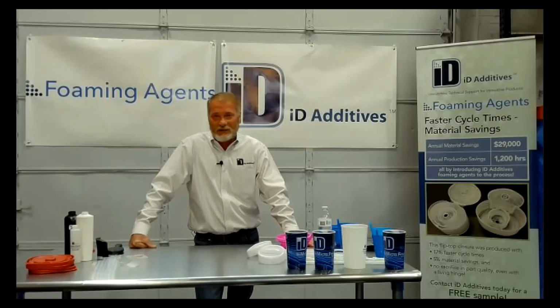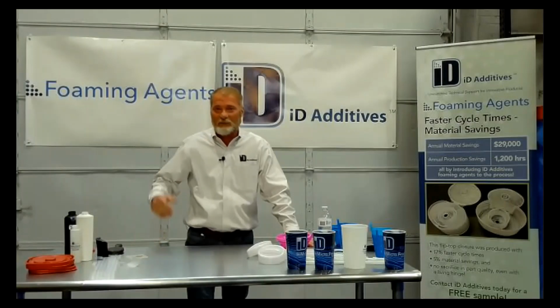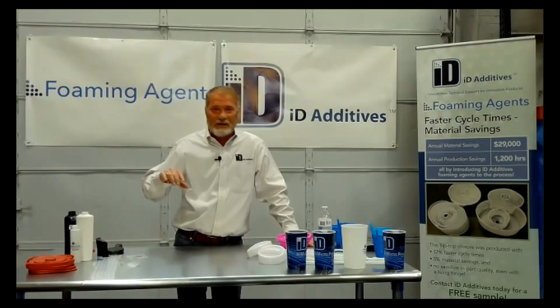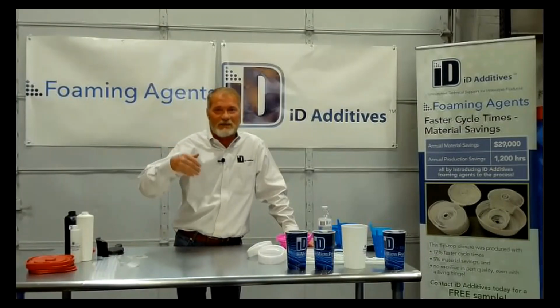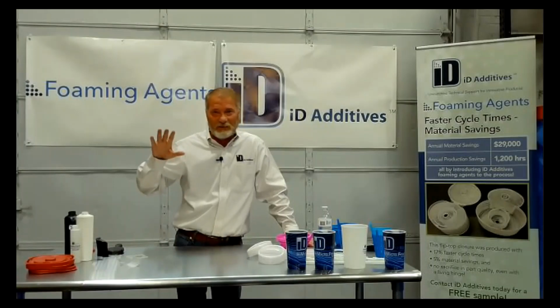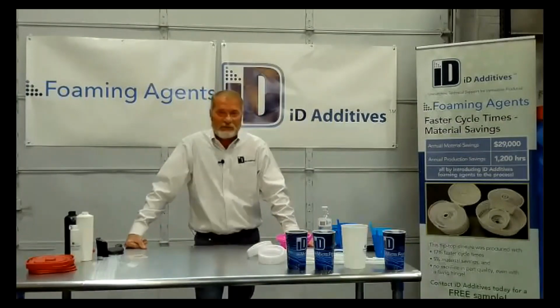And again, you take material out, you always go short, and you want to fill it, add a little more material, maximum velocity, and add material till you're just full, and that's as much as you're going to get out of it.